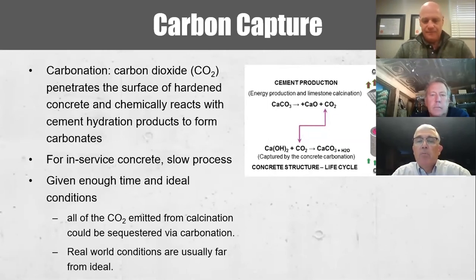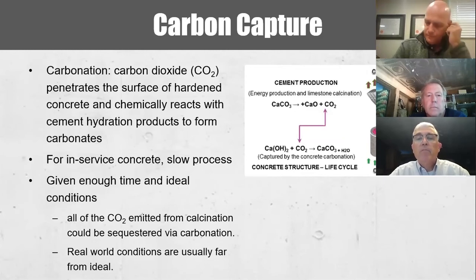It's really kind of a natural process of reversing what's called calcination, which is the process during the manufacturing of the cement in the concrete, where limestone heated to high temperature releases CO2 as it's transformed into the Portland cement product. So this is just a reversal of that process during manufacturing. It's a slow process for in-service concrete. Theoretically, given enough time and idealized conditions, you could see all of the CO2 emitted from calcination absorbed by concrete in the environment, but real world conditions are far from ideal, so that typically does not occur.